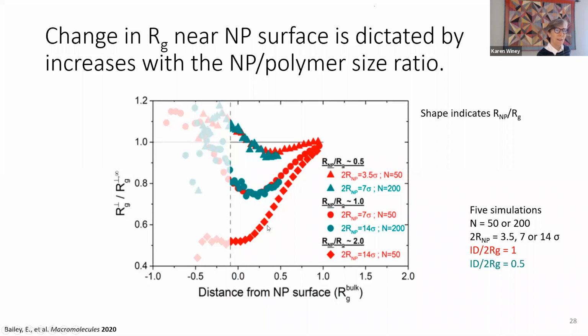But the color scheme is complicated, so let me just try and walk through this. There are 2 different molecular weights, 3 different particle sizes, and 2 different ID over 2RG values, right? But the things that line up and have quantitative agreement with one another are the systems that have the same nanoparticle to polymer size ratio. So the different shapes, triangles and circles here, indicate 2 different values of nanoparticle to RG. And so the relative sizes of those 2 objects tells us how much the chain conformation is going to be distorted near the particle.